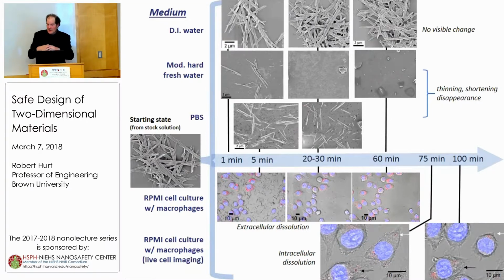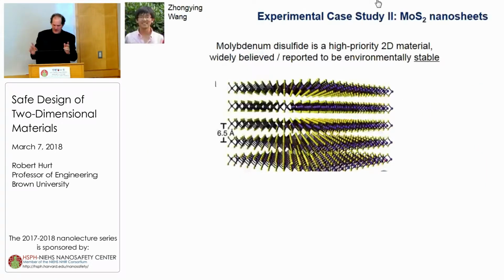Inside the cell, at the low pH in the vesicles, we see a slowed rate of dissolution, but they nevertheless do dissolve. And these materials do not elicit any adverse biological effects that we can see. They're fiber-like, but they're dissolving at the same time they're being taken up. This is a class of material that, because of its solubility in these media and the rate of that solubility, and the fact that the dissolution products have a low toxicity, we would like to select from the set of 2D materials and place in a lower priority level for further consideration.